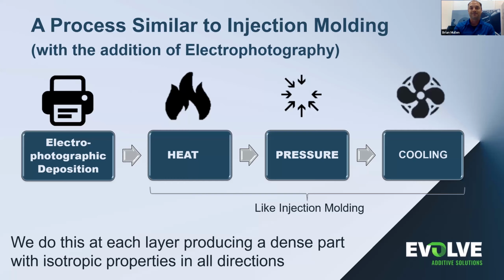So the EP technology is actually well understood. Xerox has been practicing this technology for decades. And what we can do is take advantage of their selective electrochemistry approach, in which we create these 10 micron to 25 micron thick images, and we fuse them together over and over until we create our 3D printed parts. And these very small layer thicknesses enable us to have a very dense part with isotropic properties in all directions, as well as really good accuracy.